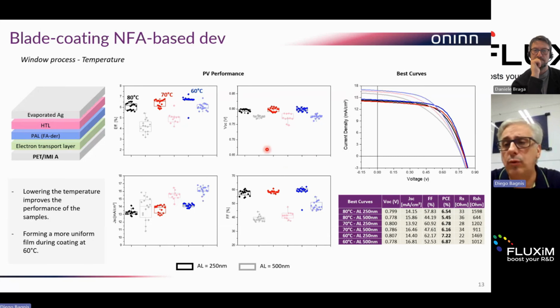But just to show that this was pretty interesting, because it goes exactly in the right direction: if we reduce the temperature, not only do we get better results, but we are also reducing the CO2 produced in the creation of the panel, and so this is a positive impact for the energy yield as well.